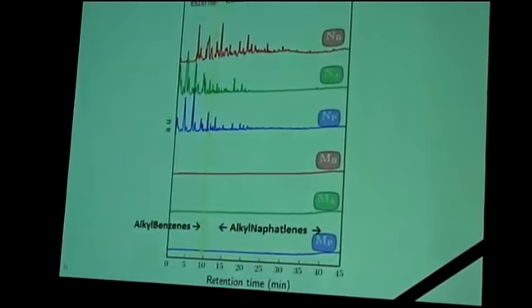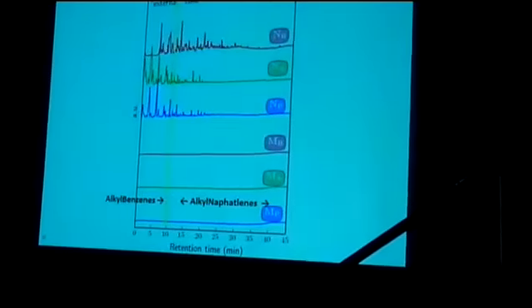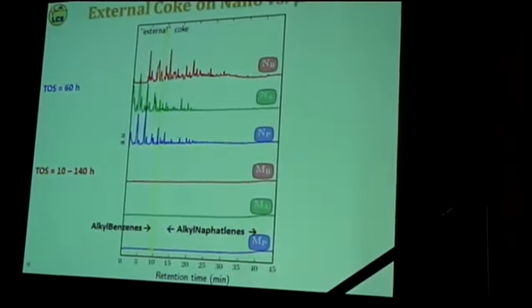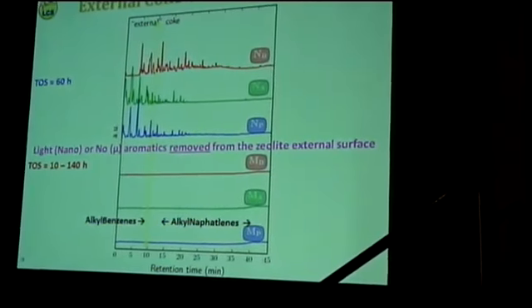We see really two families of zeolite catalysts appearing. The first one are the nano-sized zeolite, whether it's the parent or the sample that have undergone post-synthesis treatment. We can scrape a lot of coke molecules, if we call these molecules coke, from the surface, while on the micron-sized zeolites, and we know that they contain a lot of coke, and we know, for instance, that this one contains about 20% of coke, we cannot get anything from the external surface. So it should be inside. And this is what I just told you.